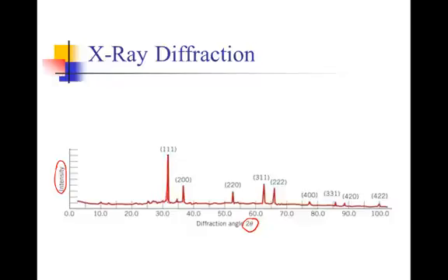So that tells us that we have a D spacing that is producing X-rays in phase with each other there. And we will have a variety of D spacings, and when we search through the computer, it matches that combination of peaks with a certain crystal type. And we can have mixtures of more than one type of crystal, and the computer can calculate for us how much of each type of crystal we have.